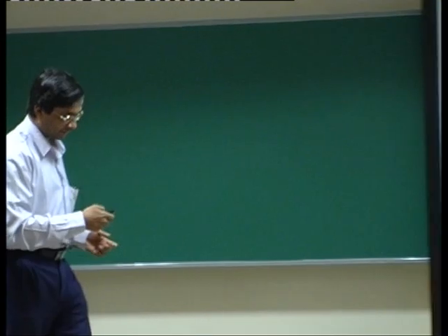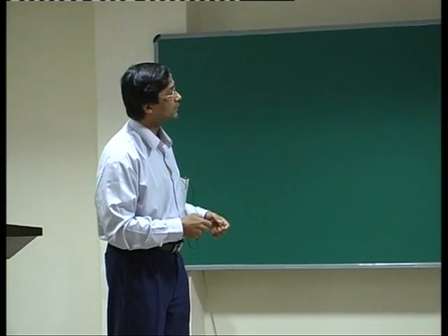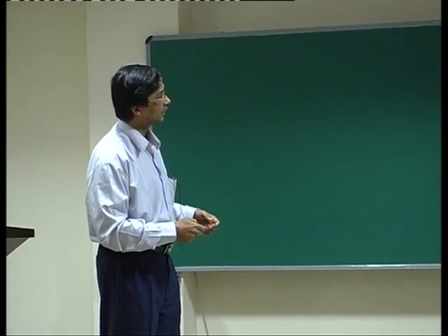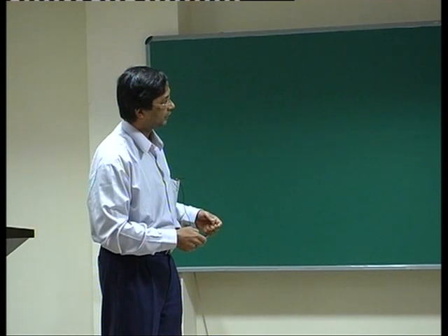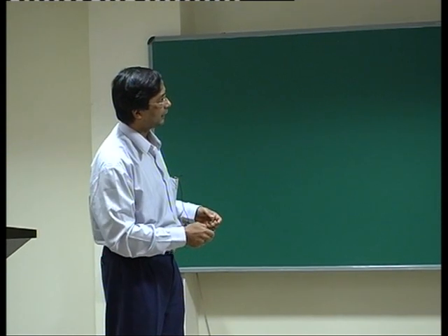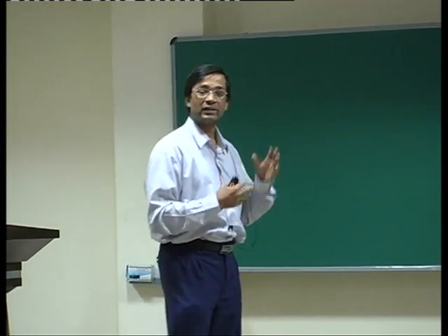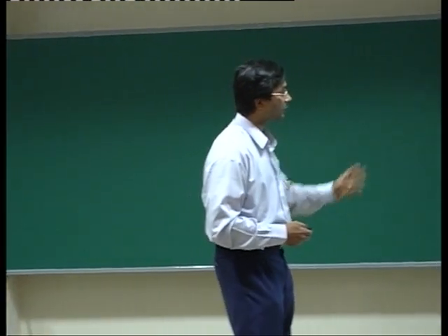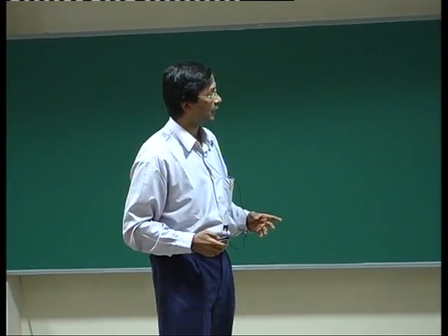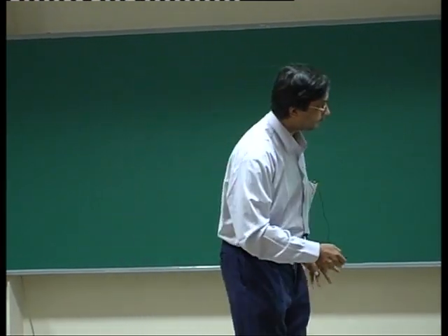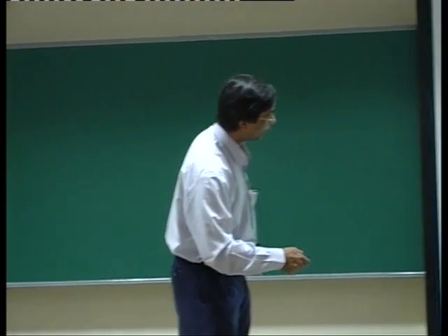And if I do that, and there's silver, just to tune your mind, what we see is exactly the kind of depletion in the occupied state and building up in the unoccupied state, this part being exactly equal to this part as it should be. It's nothing but the Fermi-Dirac distribution. So keep that in mind, and then when you look at the nickel sulfide case, it's shown over here, forget this line for a moment.